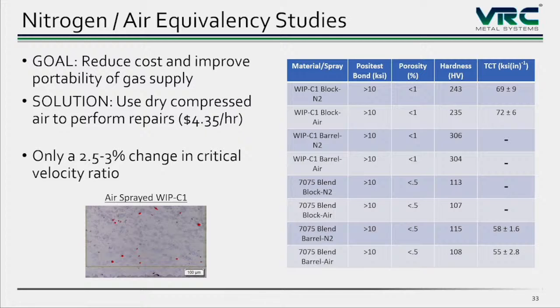Now our predictions say that we should see something like a 2.5 to 3% reduction in the critical velocity ratio going to air. So where does that show up? Well, so far the only place it's showing up is in hardness. And while I guess it's debatable because the differences you're seeing are all within the typical scatter of a Vickers hardness test, you can see consistency from nitrogen to air where you are getting a little bit of a drop each time when we go from nitrogen to air. So we are seeing a slight difference. However, that amount of difference can be easily made up with process conditions. Modify process conditions and you're back to where you were with nitrogen.